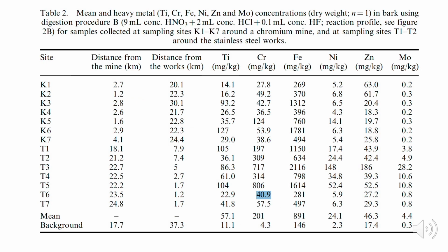This table contains the test results in the bark for several different metals. You can see in the last row that the background concentration of chromium was 4.3 milligrams per kilogram, and that the average across the T sites, which are those near the ferrochrome and steel production facilities, was 81 times higher at 201 milligrams per kilogram.